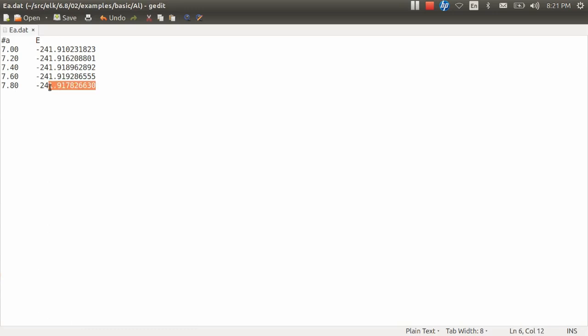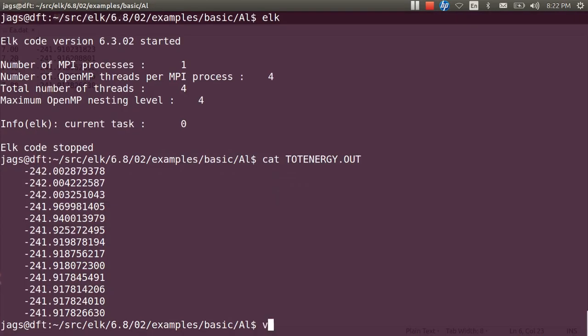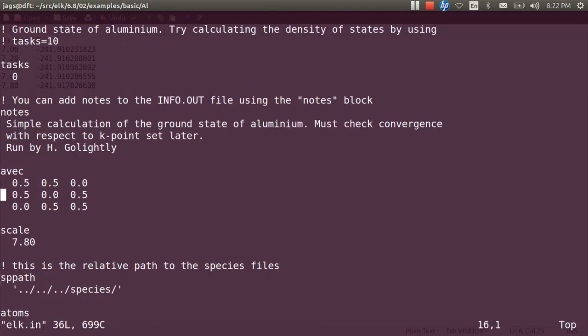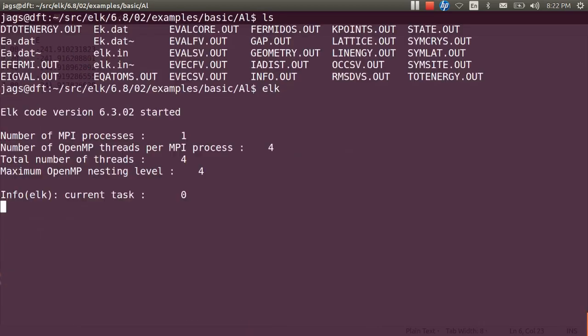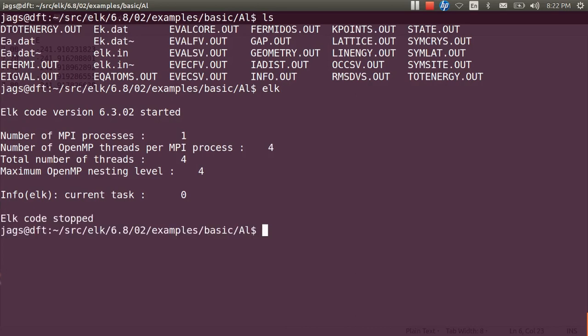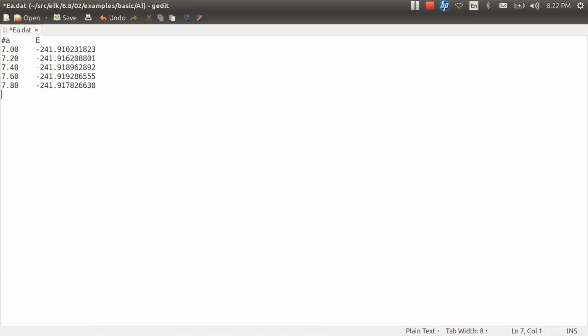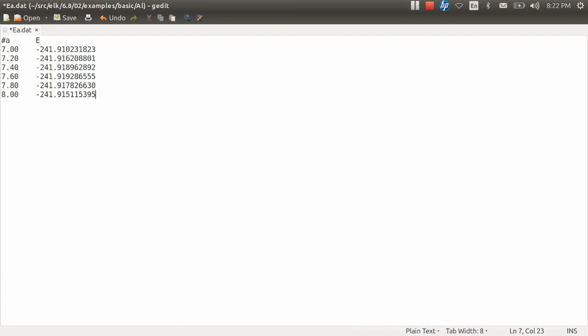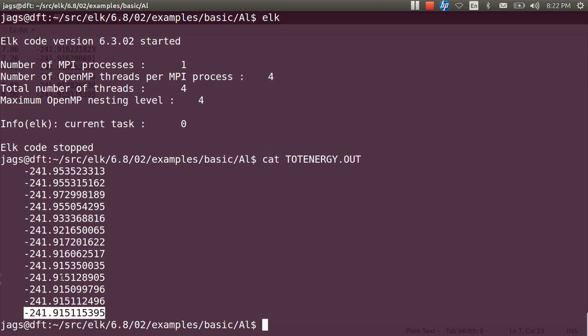Now you should see, up to this point there was a decrease in energy. Now energy started to increase. This shows that the minima should be somewhere between 7.4 and 7.8. This may be some mistake. We should cross-check for some further higher value of lattice constant, so as to get that proper shape of the curve. When I show the plot, you will realize what does it mean. Let us do one calculation for 8.00. We are doing in steps of 0.2 Bohr. I hope you remember the units are Bohr, right? Now again you would see the energy has been further increasing. Say 8.00. Now this exercise you can do in detail.